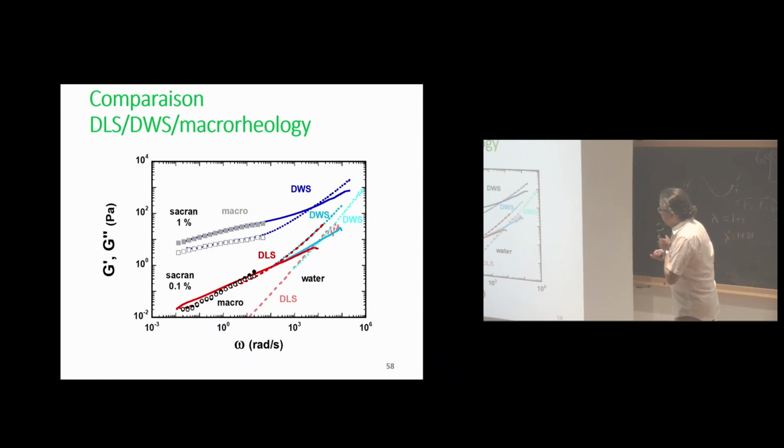And we can compare microrheological techniques and classical shear macrorheology. The macrorheology data were taken by Guillain, so you can see these data points of macrorheology, and all these colored curves from microrheology, and they superpose reasonably well for this system. It can cover, let's say, down to 10 to the minus 2 Pascal, but it's getting less accurate. At higher modulus, it can be thousands of Pascal. At 10 kilopascal, it's already very difficult, as we use only the thermal energy kT. When the system is elastic, the displacement can be too short to detect even with DWS. So we can check the validity and accuracy of the technique by comparing with macrorheology.